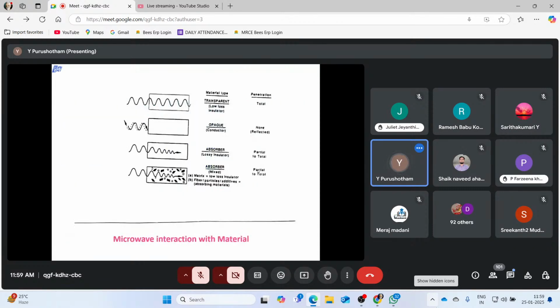Here you can see how microwave interacts with the material. If it is a low loss insulator, it is totally transparent. If it is a conductor, such as metals, the microwaves don't penetrate. Whatever comes from the generator, called the magnetron, will reflect back if you keep any metal, and it may damage the magnetron, the microwave source itself, because metal is not at all possible. If you want to melt metal, you have to use either resistive heating or induction heating, but microwave is difficult. So these are all material dependent procedures.